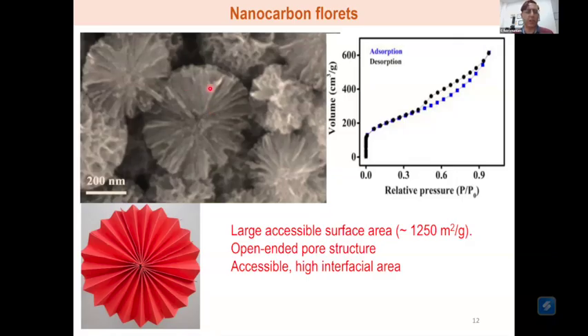And this cross section actually resembles very closely a Japanese origami fan, which basically has a broad mouth or opening on the surface, and that is continuous and extends all the way to the center of this material in the form of a continuously graded pore structure. If you imagine the structure, you take a cone and assemble these cones against each other in a 360-degree fashion, you get this entire three-dimensional, isotropic structure.